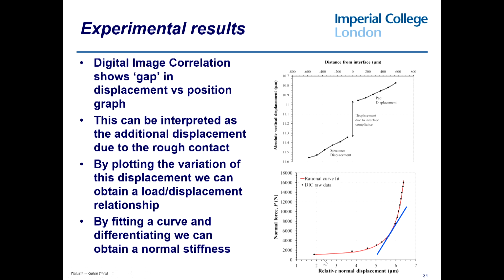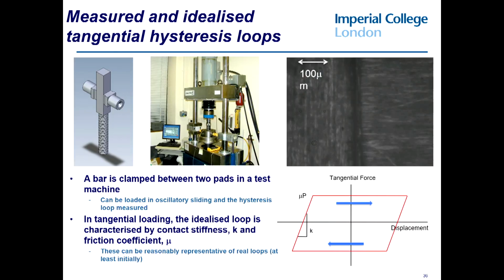And what you can see is that the contact stiffens up. That we start here, we get a lot of displacement for a small amplitude and load, and as we go round here, we get much less displacement for our increase in load. We have studied that both at Oxford and Imperial. We've got different rigs, but essentially you get very similar results.